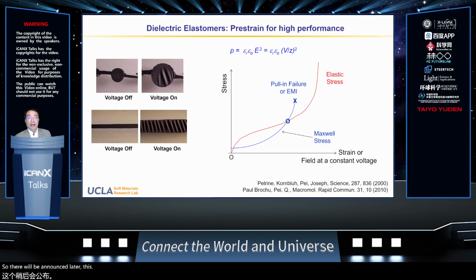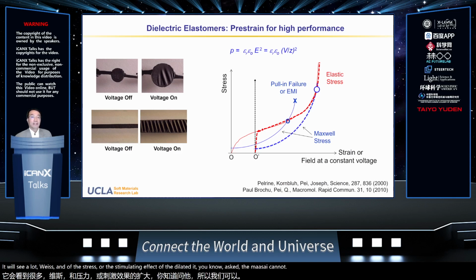Okay, so the stable actuation you can get from this film is limited because of this electromechanical instability. What the pre-strain does here is that it narrows the plateau of the stress-strain behavior, so that when the true field rises to a certain level, it will see a rapid rise of the stress, or the stiffening effect of the dielectric elastomer. So you cannot expand it infinitely. So we can achieve a much larger stable actuation strain from this pre-stretched film.